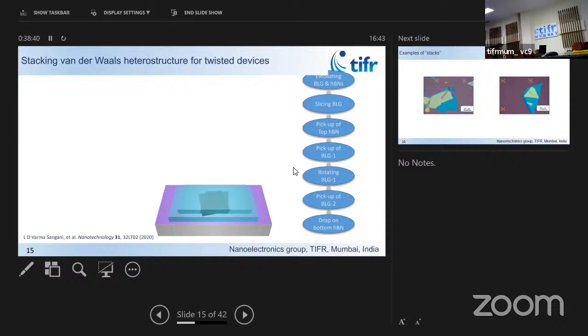I should say that this twisting realizes a kind of artificial two layers which are not thermodynamically stable. So you have to vary them a fair bit. Sometimes the angle in the actual device doesn't turn out to be the angle that we dial. But you can verify what the actual angle is in the device, even to an accuracy of something like 0.02 degrees, from the transport measurements.